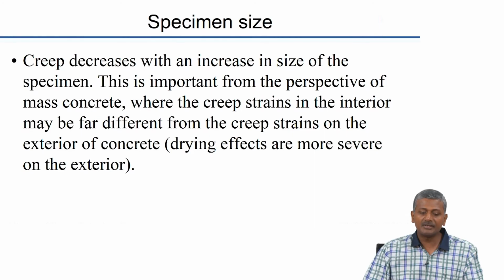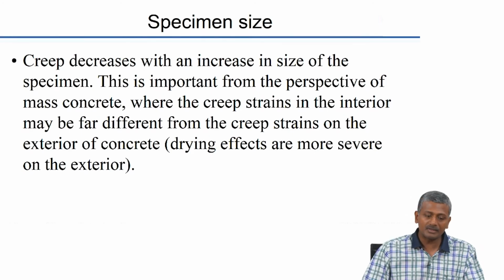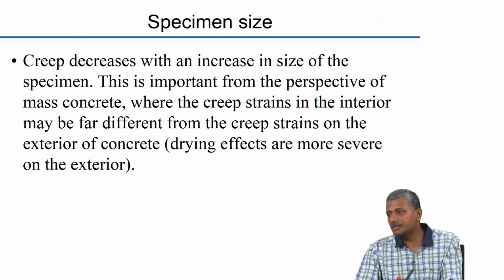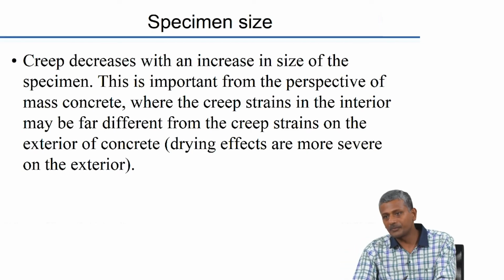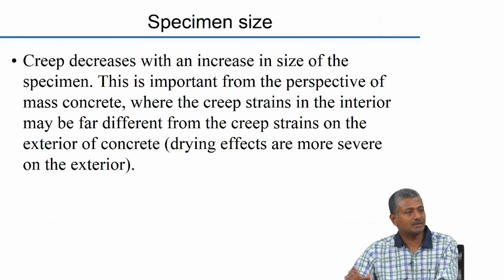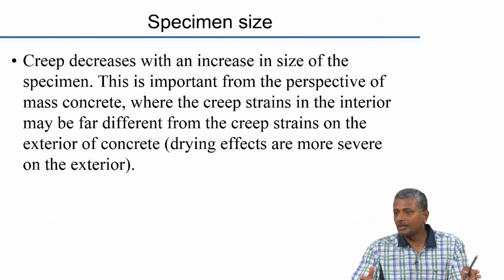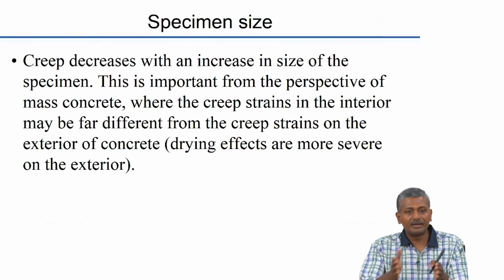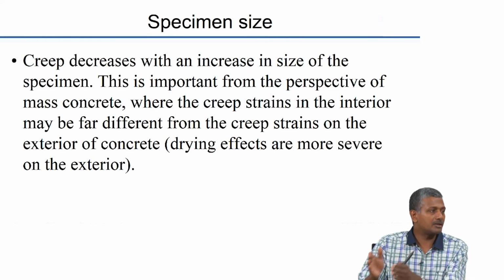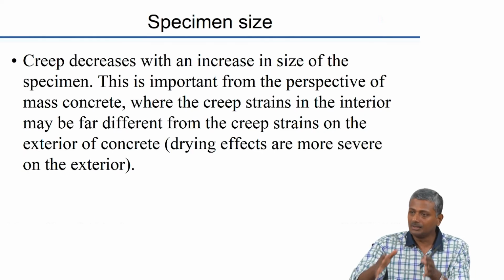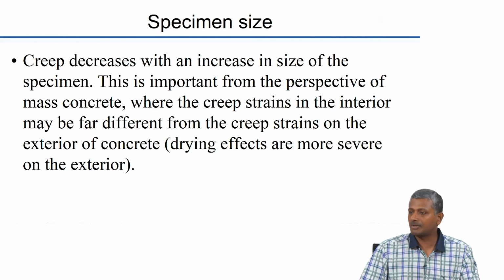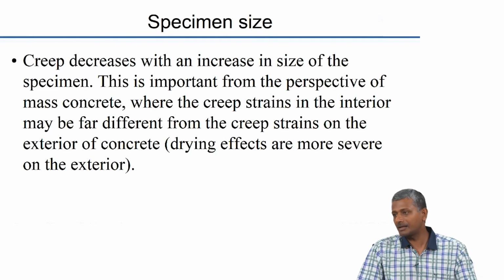So, creep strains in the interior may be far different from creep strains in the exterior, because in the exterior it is not just the load related effect, it is also the drying effect which can increase the level of creep on the exterior. So, within the same material or within the same structure you can now have a region with lower creep and a region with higher creep. So, there are differential strains that are created because of creep in the system, and that may lead to cracking.